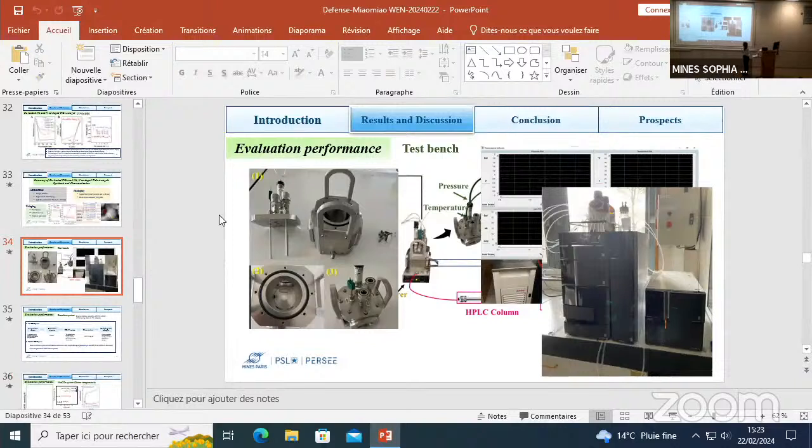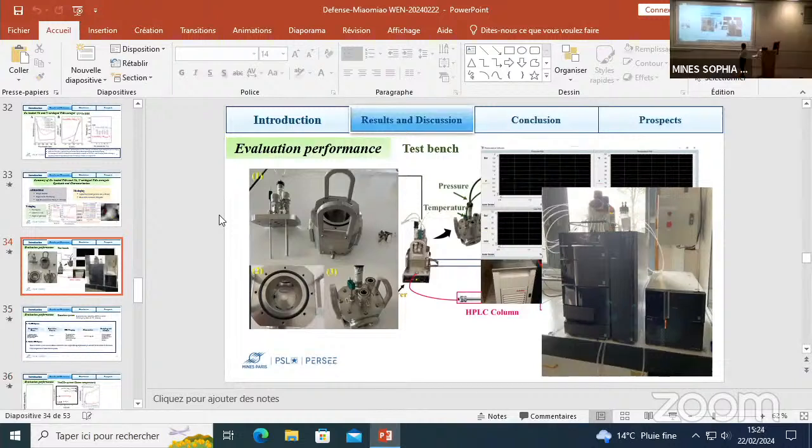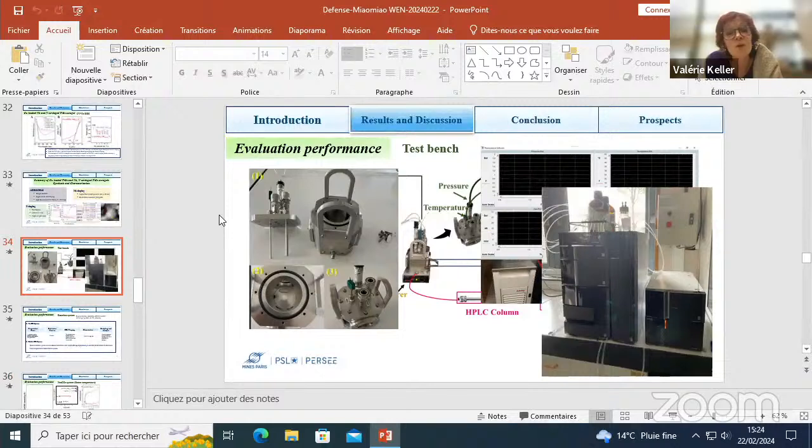Are you sure the carbon in the methanol really comes from the CO2 that you are feeding or from sodium carbonate? Did you perform the test without feeding CO2 or without adding sodium carbonate, to be sure that there is not another source of carbon?